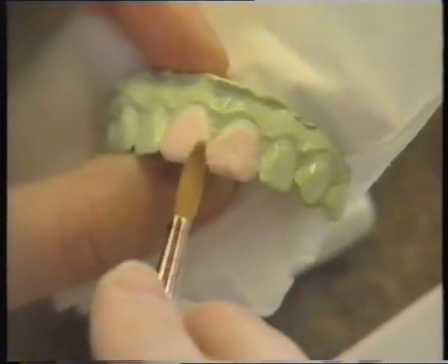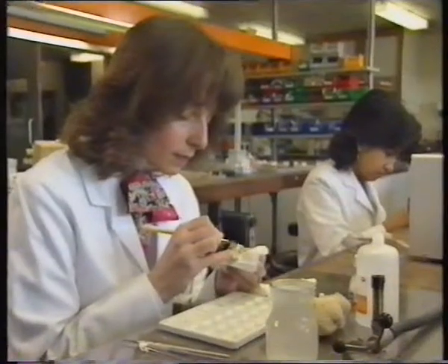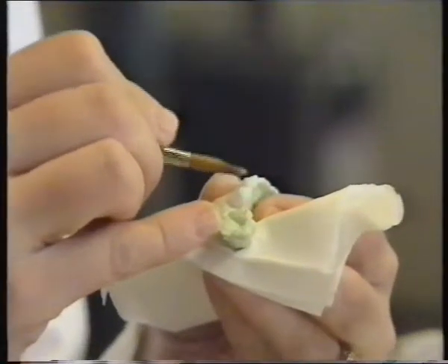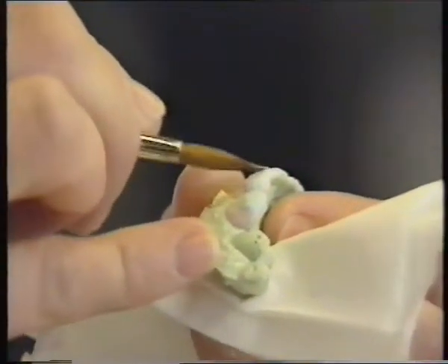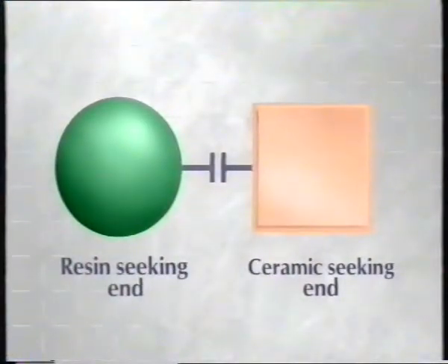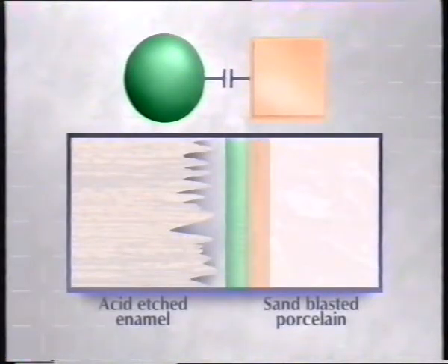Veneers of porcelain can also be bonded to enamel via the acid etch route. However, in order to obtain a bond with the porcelain, its fitting surface has to be roughened, either by etching in the laboratory with a hydrofluoric acid derivative or by light sandblasting. To enhance this mechanical bond, the veneer is coated with a layer of a bifunctional primer called a silane. This has the ability of forming a chemical bond to both the porcelain and the composite resin.